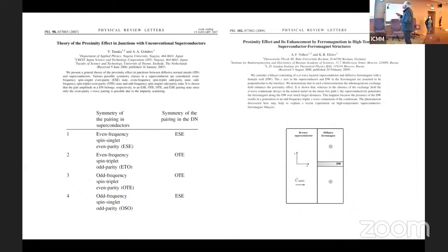In this paper, they precisely address what the pairing symmetry would be between a high TC and a ferromagnet. What they proposed is that in the same symmetry that we have, with the C axis perpendicular to the ferromagnet, if there is a domain wall, and we have plenty of them, with its plane perpendicular to the superconducting layer, there is a mechanism of conversion of the D wave into S wave. So there is at least a theoretical argument that there may be a conversion into S wave in the ferromagnet.